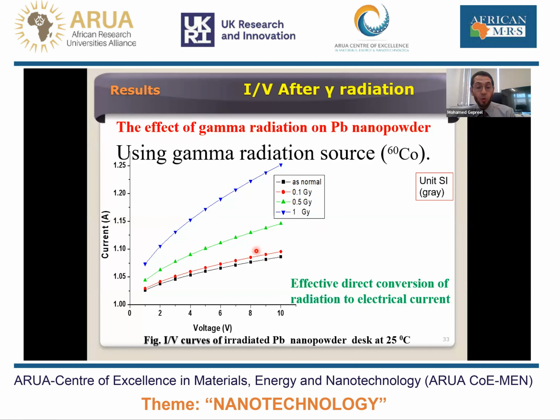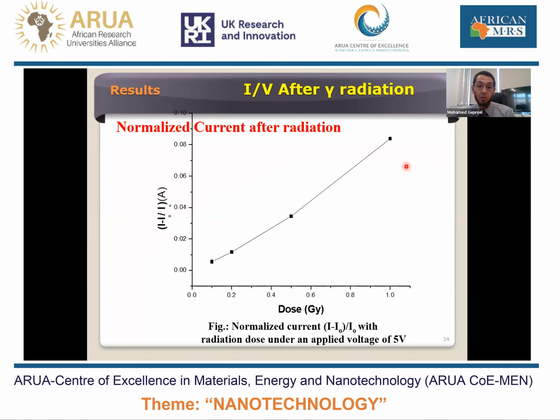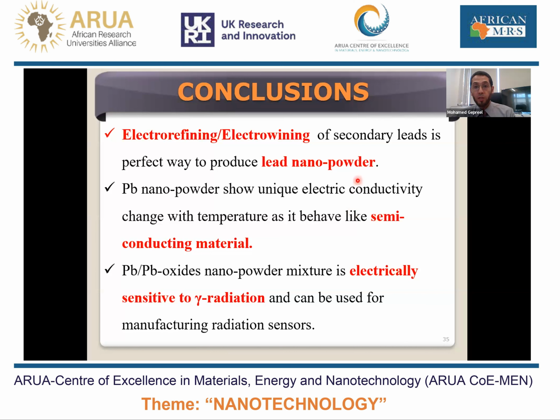So we can see again that this type of disk can sense the radiation level, as a function of the volt and so on. So it's very easy to calibrate and detect the level of radiation, for radiation of cobalt-60 and so on. And this is how to normalize the current change with the dose. So this means it's easy to calibrate and to make a sensor from such a lead oxide, lead nanoparticle mixture.